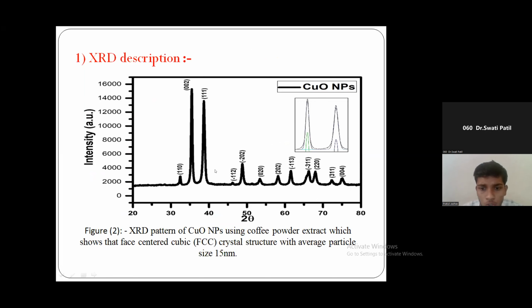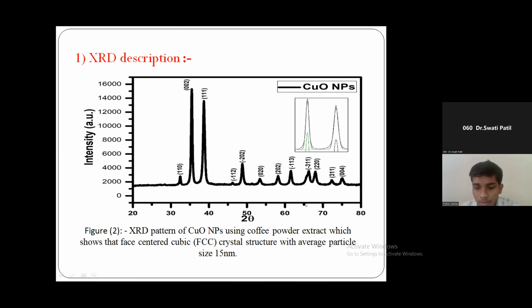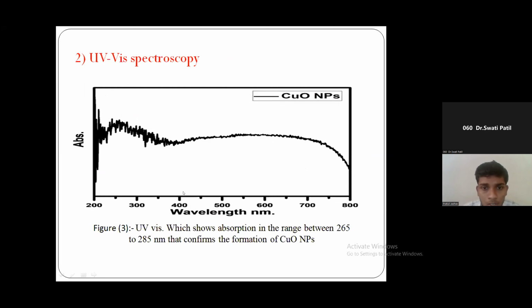This XRD pattern shows a face-centered cubic crystal structure with an average particle size of about 15 nanometers. And then here is the UV-visible spectroscopy. This shows the absorption range between 265 to 285 nanometers, and that confirms the formation of copper oxide nanoparticles.